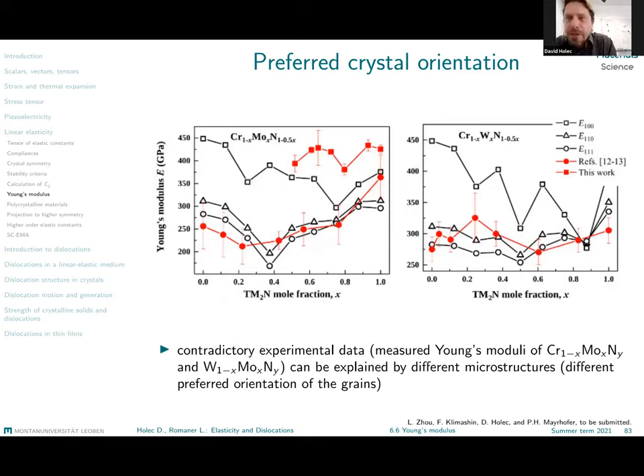In this picture, we show that even experimentally, you can determine this directional dependence of the Young's modulus. As soon as you correlate the directional Young's modulus with indentation modulus for a nicely textured material, then you are going to load your material essentially in one direction, apply the force pretty much in one direction. As much as we can say that this can be related to a uniaxial loading, we can try to relate